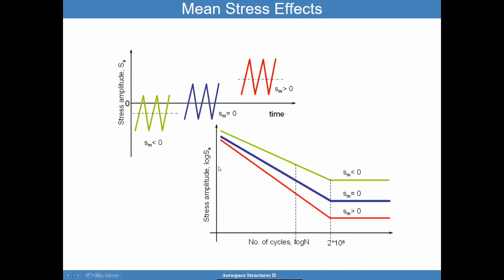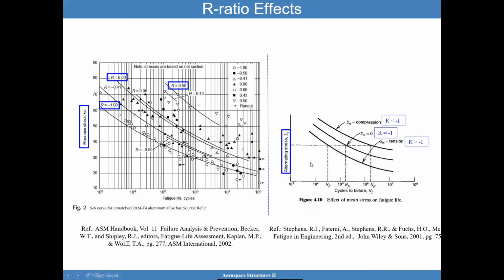So if I have a mean stress as less, this slope is going to be better, and your endurance limit will be higher. But if everything is in tension, including mean stress, then this slope will look steeper, plus the endurance limit is lower. So as you can see here, mean stress effects do play a significant role. Possibly the majority of your tests may be done at fully reversible. And so now, as you can see, the R ratio, which is sigma min divided by sigma max, becomes important. And again, SM equals 0 is R equals -1. And so then it becomes important to understand the effects on the various testing that exist.